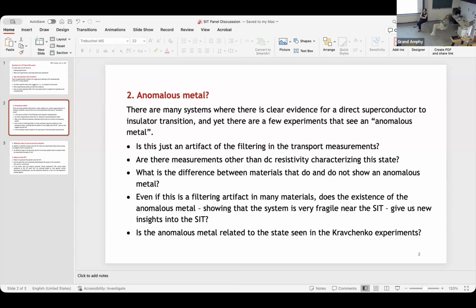Imagine that you have this metallic environment, in the holes of which are superconductors. And within this metal, you have regions which are insulating. So you can imagine a transition between the insulator and the superconductor. Just imagine that you have a smooth potential, and Tc in this region is bigger or smaller. Then when you lower the temperature, some parts become superconducting, some not. And in the parts that do not, is that an insulator that is locally localized?